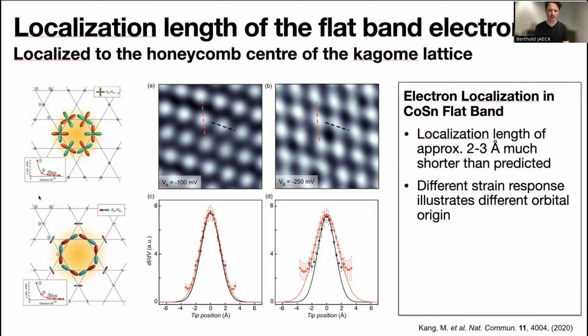Now, if this is the right way to determine the localization length, how to tell? It's obvious that what we do here is we basically overestimate it. You can see the red line already goes up here. If I were to put a second Gaussian here to pick up the next spectral wave, it would already contribute to this one. In other words, the real localization length would be even a little bit shorter.